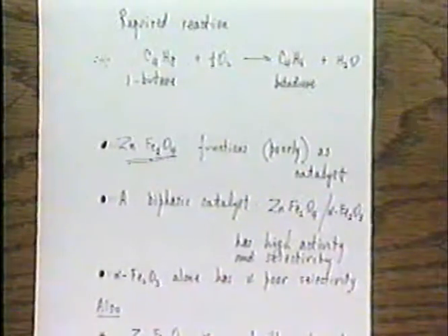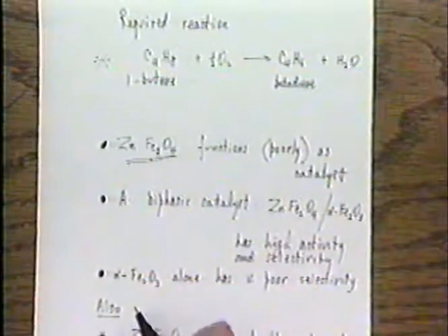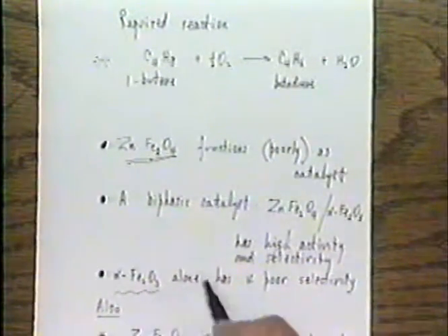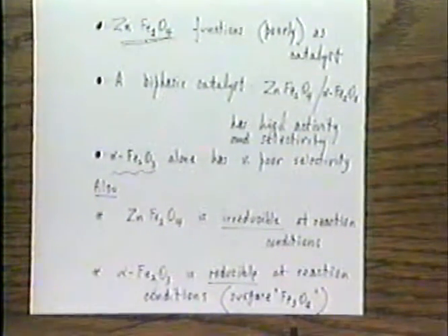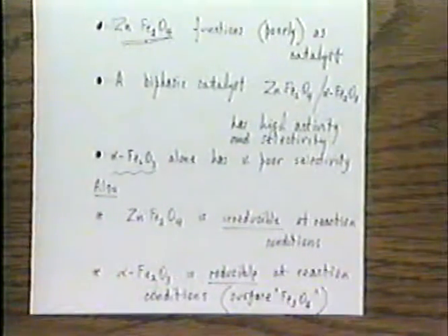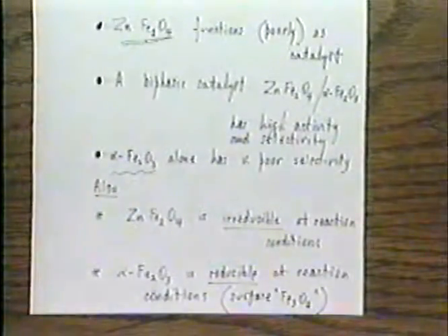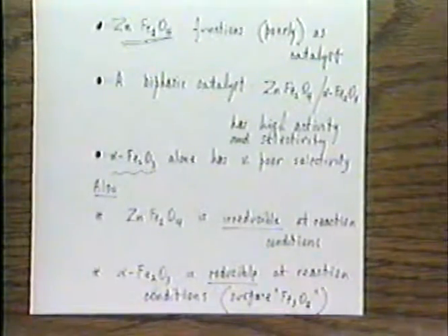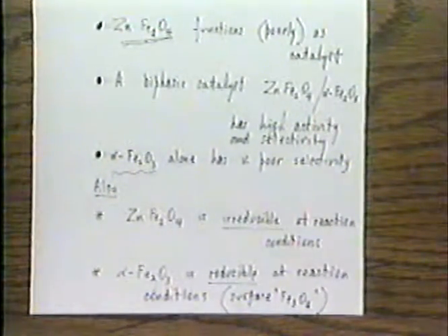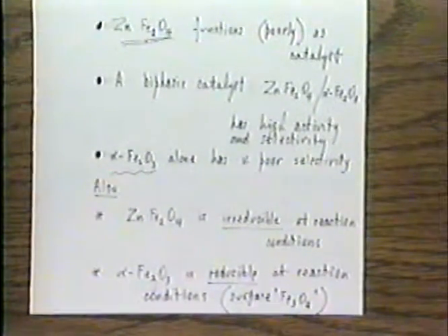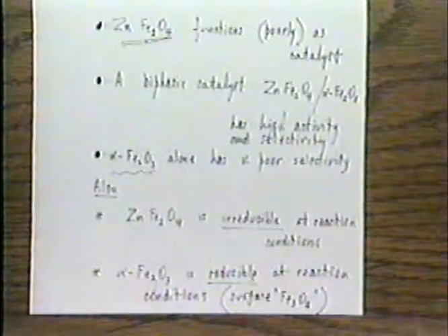On the other hand, it was known, and it's well known for a long time, that Fe2O3 is able to adsorb oxygen by electron transfer because Fe2O3 is readily reducible to contain Fe2+ ions in the surface, and that's exactly what you might expect if you reflect upon the fact that Fe3O4, which is a stoichiometric material, of course, is a substance that can be prepared from Fe2O3 by partial reduction.